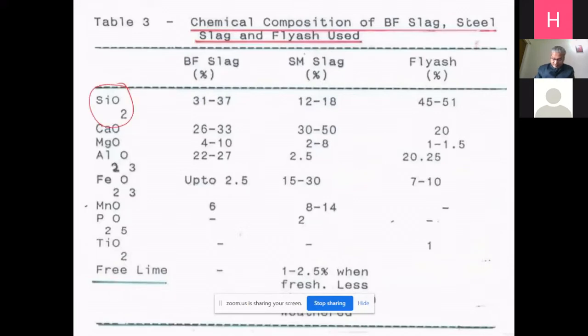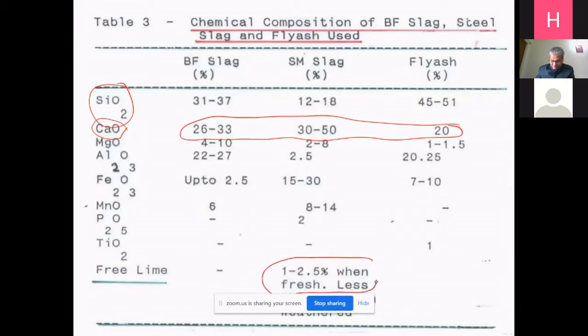and after that, the strength comes from calcium oxide. Calcium oxide is basically lime. So the strength is coming from this portion. But due to this lime, there is one problem also: this steel making slag or SMS has 1 to 2.5% free lime also.